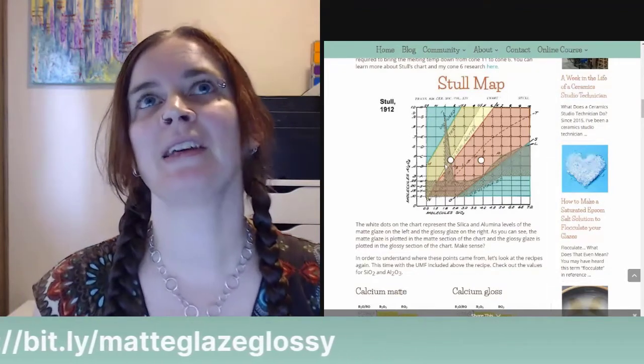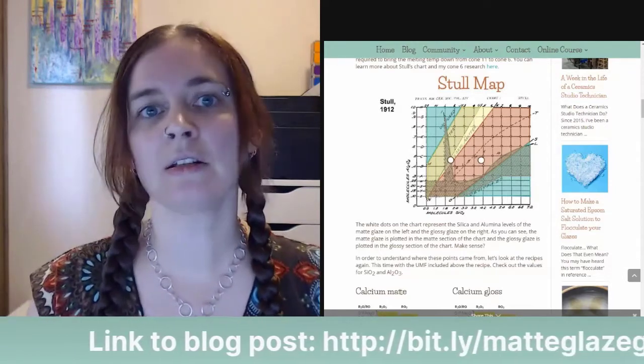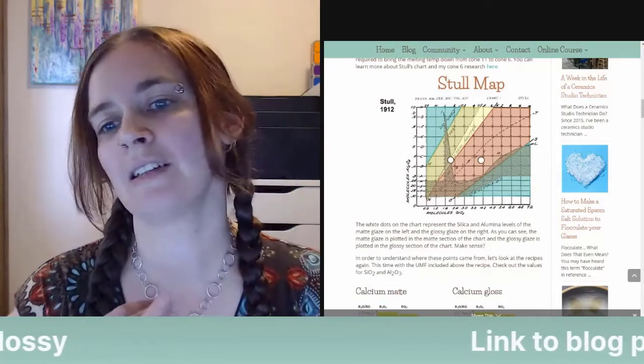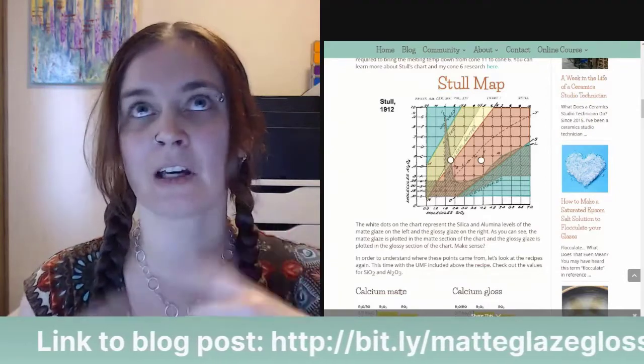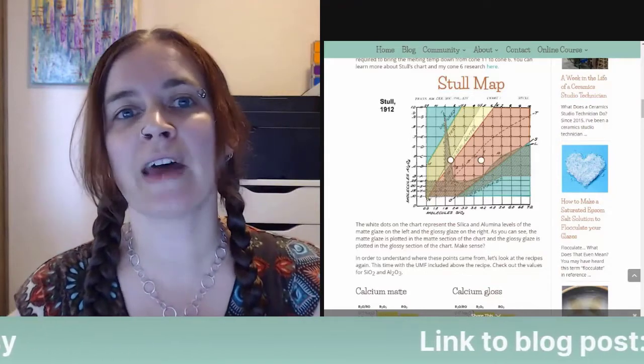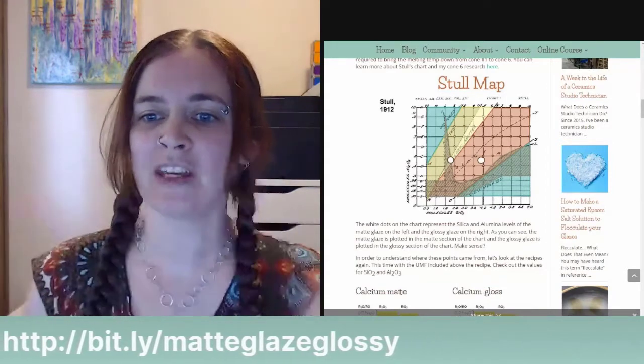So the problem with this is because we get silica in our glaze recipes from lots of different materials. So it's not always silica as an ingredient. Feldspars contain silica, frits contain silica, wollastonite and talc both contain silica. Our clay contains silica. Silica is provided to our glaze recipe from all these different sources. And so it's possible that your glossy glaze recipe doesn't have enough silica just as a standalone material in order to remove enough of it to move it into that matte region.